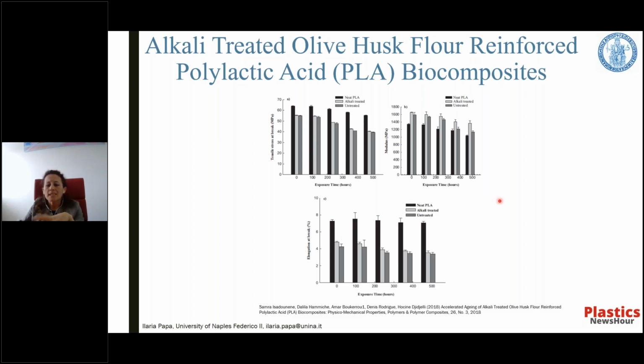Some of the samples were subjected to accelerated aging treatments in order to study the characteristics of the compound in different phases of the usable life of any product. And I haven't shown it in the slide, but from the DSC analysis, it's observed that the pure PLA samples have a higher melting temperature after accelerated aging, given the embrittlement of the surface following the process, while for the compounds, whether alkaline treated or not, the temperature decreases.